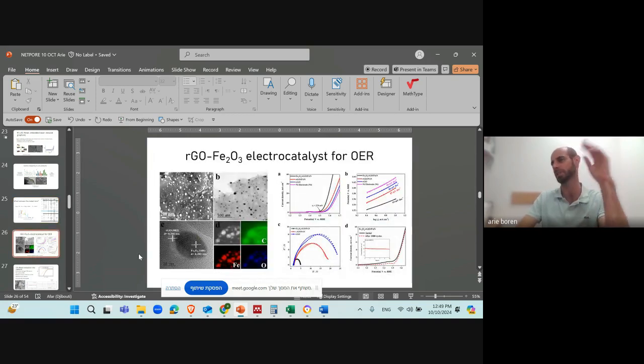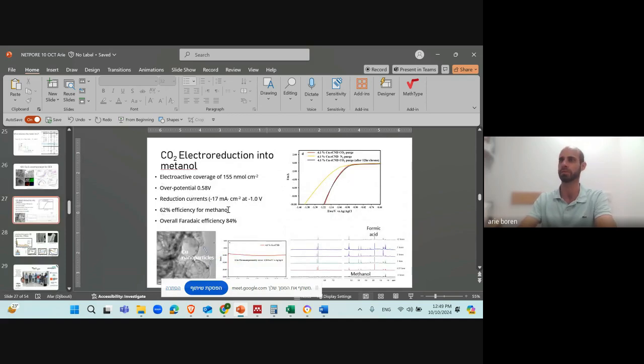Okay, this was just two applications, and I will finish with it. We have two more slides. So one is we used iron oxide to electrocatalyze OER. Okay, so we have very nice results with this. And also for CO2 electroreduction, we use, of course, copper. So we have copper nanoparticles in this graphitic matrix, and you see the onset potential, if we added the CO2, dramatically going down.